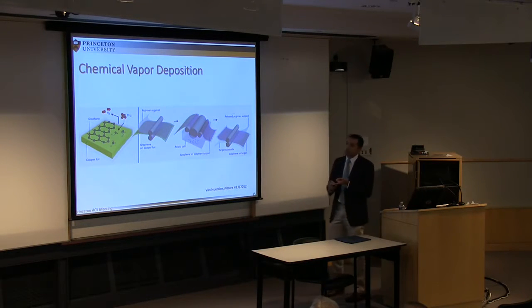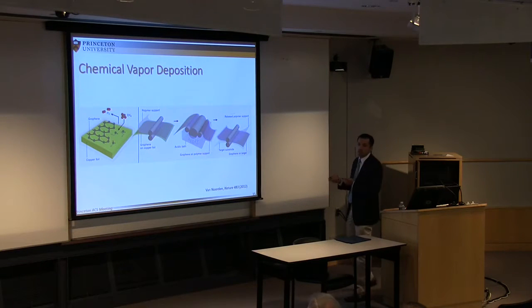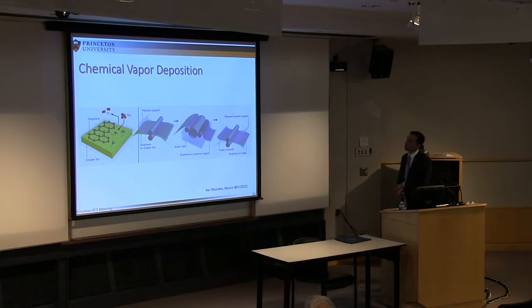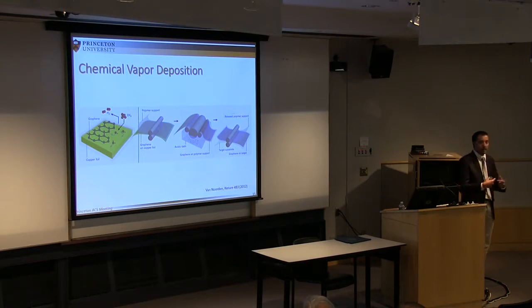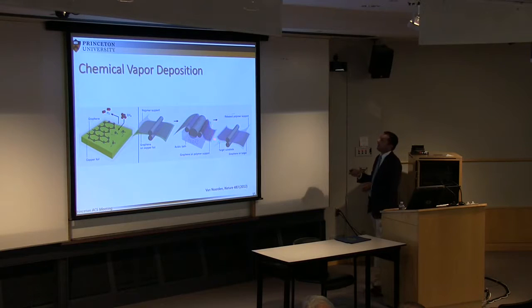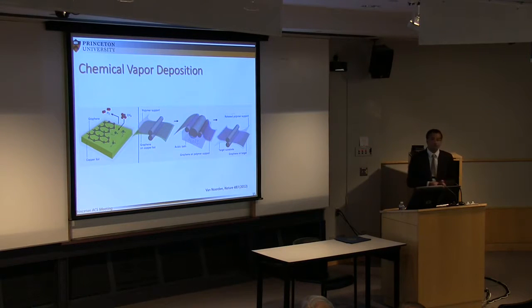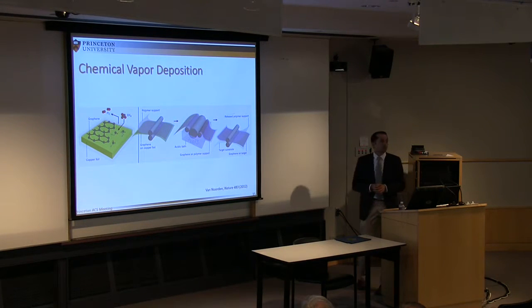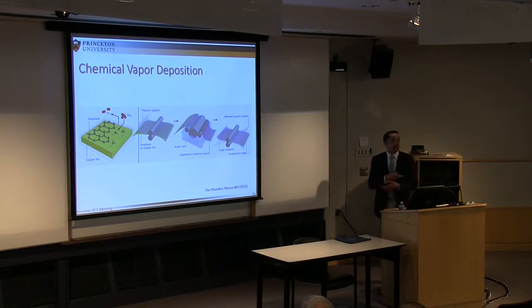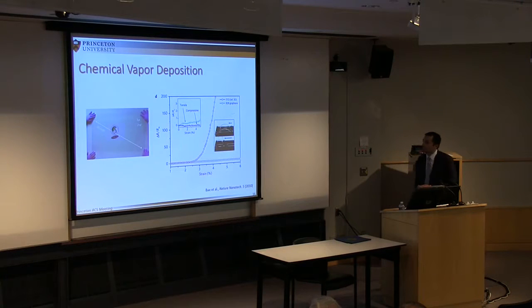So what do you do? This work was developed by the university in Korea in collaboration with Samsung. What they did is they transferred the graphene from the copper onto a polymer first using a roll-to-roll mechanism. Then they etch the copper away, and ultimately they release the graphene layer from the polymer to the target substrate. In this case, it can be another polymer, or it could be glass, anything. So it has several advantages, CVD.